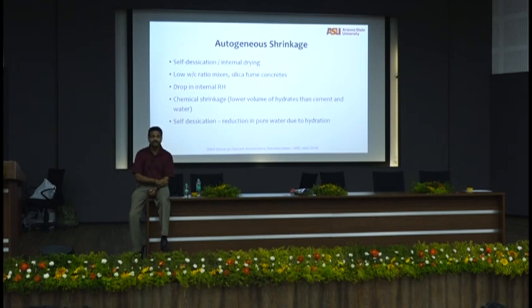If you have materials that react very differently in a system, right? You have materials that really have expansion that's happening in the system very early on, then you talk about chemical shrinkage. If you use a very low water cement ratio concrete to get ultra high performance concrete, then talk about autogenous shrinkage. Use it for the right context. Don't take a 0.4 OPC standard concrete and start testing all of these. You wouldn't need it. You wouldn't know any difference. Context becomes very important. Okay?